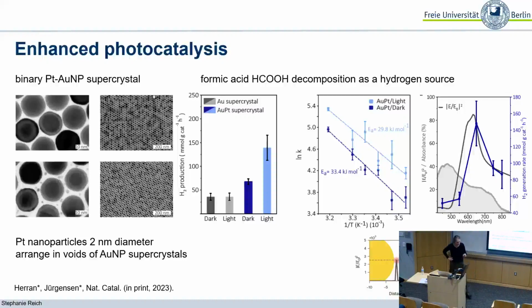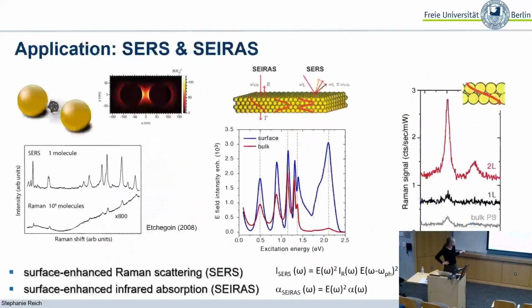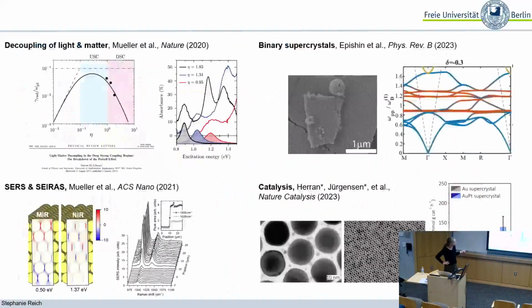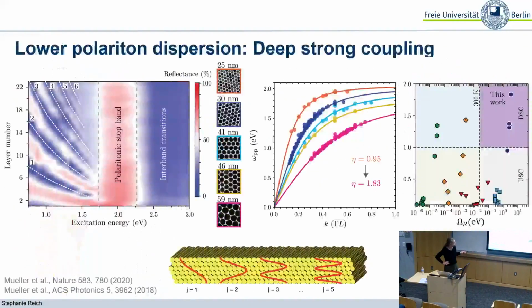Very small we did not do, but we did small ones, I think down to 12 nanometers, that was the smallest one. This year it's only down to 25. So this year is between 25 and 60. And it's the same ligand, right? So everything is the polystyrene ligand. It's the same type of polystyrene ligand, but different weight sometimes.